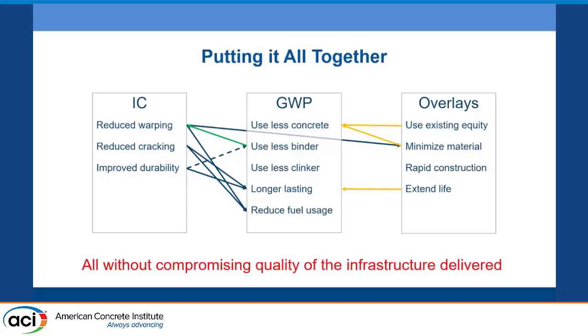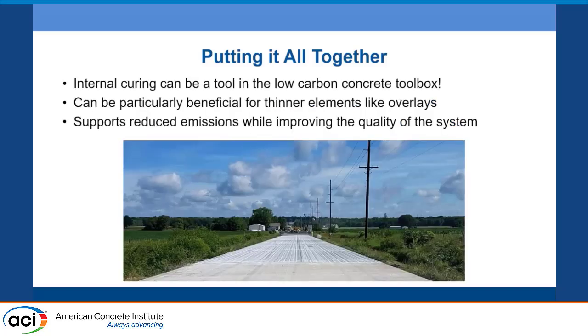And I think based on the test sections that were built in Iowa several years ago, we've seen quite a bit of evidence that we were able to enhance the performance of those concrete overlay sections. So in conclusion, internal curing does appear to be a good sustainable solution, not just for buildings and bridge decks, but also for our concrete pavement infrastructure. And overlays does appear to be a particularly good use case, given, again, it's a thinner pavement element. It might be more susceptible to curing related issues, and so internal curing could be particularly helpful there. And, again, it supports reduction in carbon emissions while also improving the quality of the system.